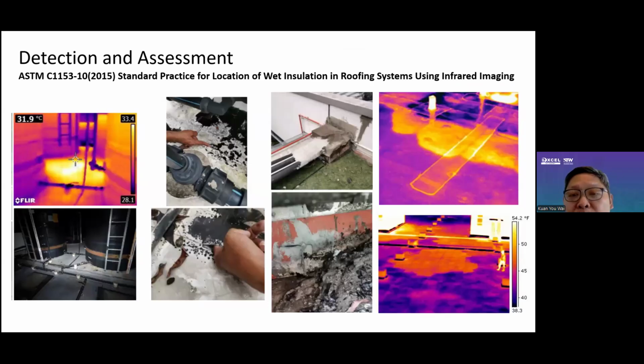Okay, how do we check waterproofing failure? ASTM C1153 is a standard practice for locating wet insulation in roofing systems using infrared imaging. Imagine if we have one piece of concrete slab, some area have water pocket due to waterproofing failure, some area doesn't have water pocket because there's no waterproofing failure. So the flat roof will absorb heat, be it with water pocket and without water pocket, equally. But in the evening, we can use infrared to identify the water pocket because the water can retain the heat longer. So in the evening, we actually look for hot spots and we confirm the water pocket using a moisture meter that can penetrate up to 20 mm.